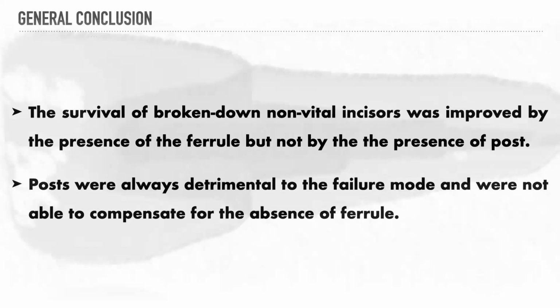So the general conclusion about our two studies is that the survival of the broken down non-vital incisors was improved by the presence of the ferrule, but not by the presence of the post. So the ferrule is the most important factor in this kind of teeth. So we need to preserve them. And the posts were always detrimental to the failure mode and were not able to compensate for the absence of the ferrule.